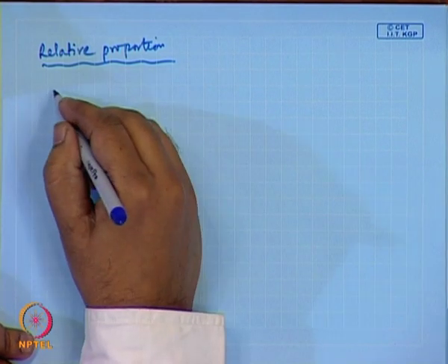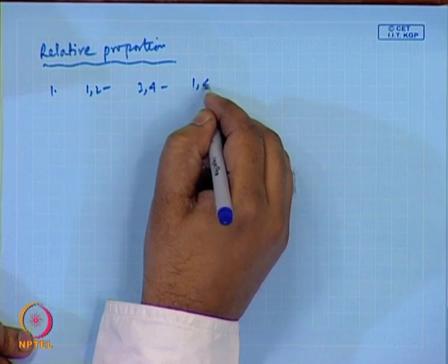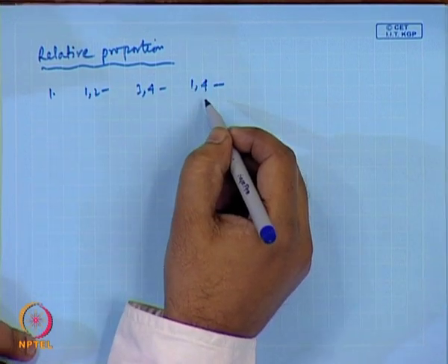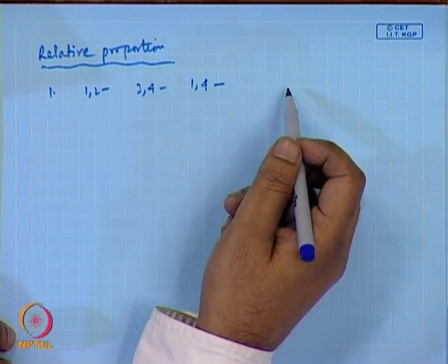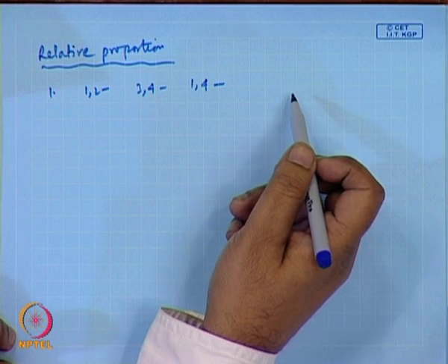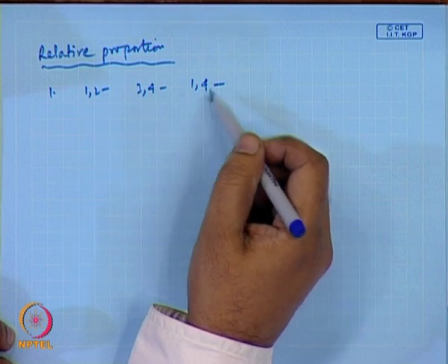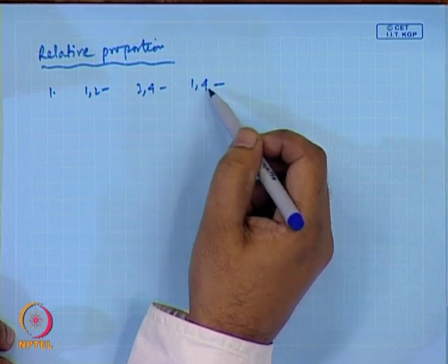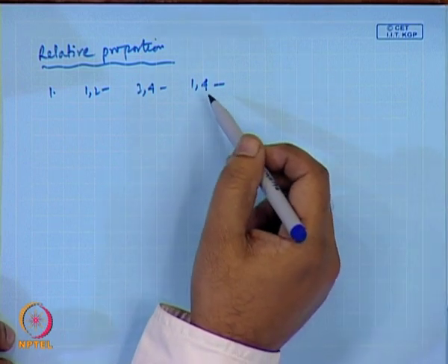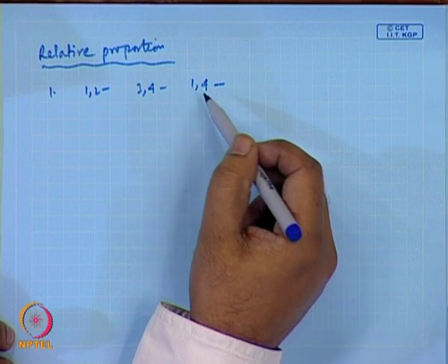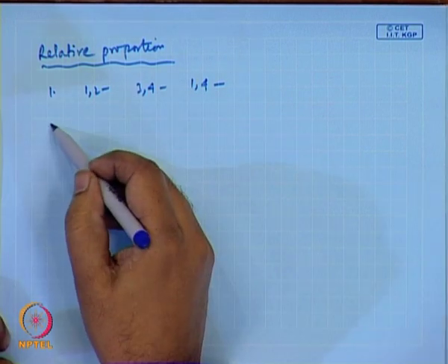Obviously, between these three it will be the addition which gives the intermediate having the lowest energy that will be the predominant product, and in most cases, because the 1,4 addition gives a longer resonance stabilization, this is the preferred propagation mechanism compared to the other two.